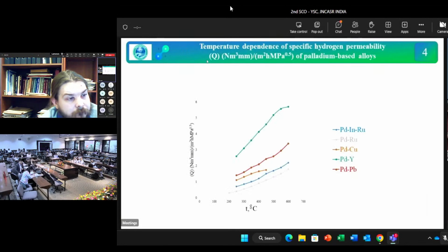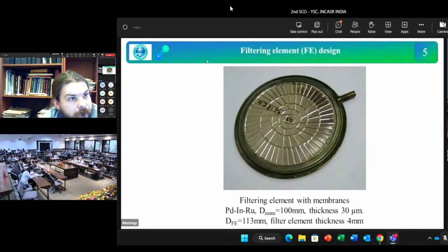This graph demonstrates one of the principal membrane characteristics, namely the specific hydrogen permeability of a number of membrane palladium alloys with yttrium, lead, copper, ruthenium, and indium with ruthenium. The structure of the alloys corresponds to a palladium-based solid solution. You can see the image of the structure of the filtering membrane element. The filtering element consists of two palladium membranes, profiled steel frames, a porous separation element, and a nipple for gas output.